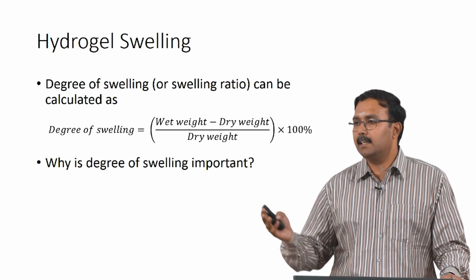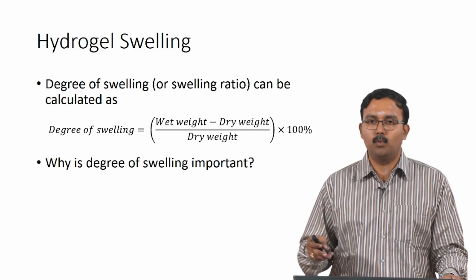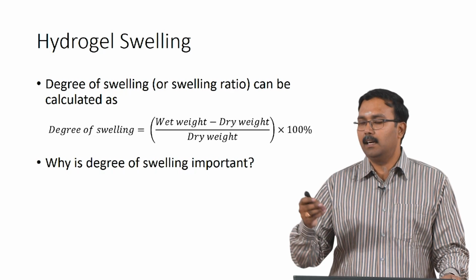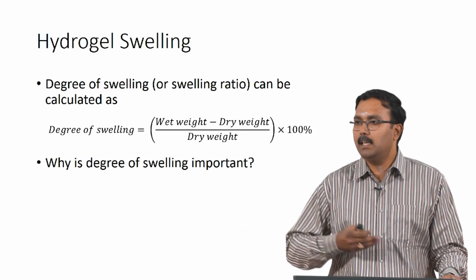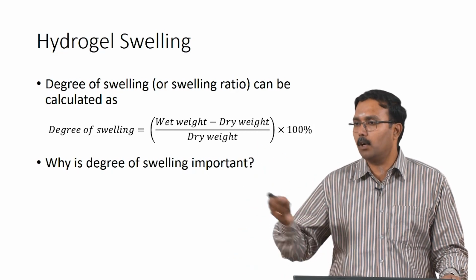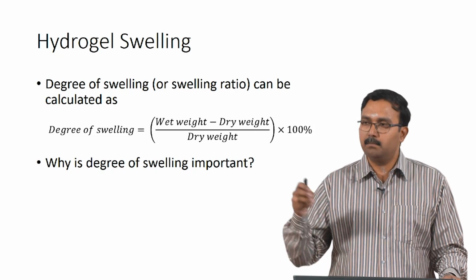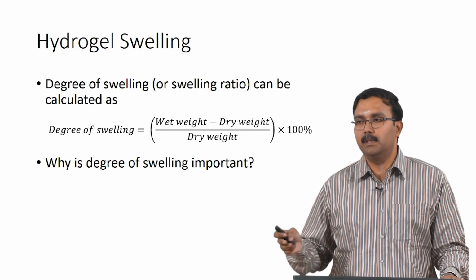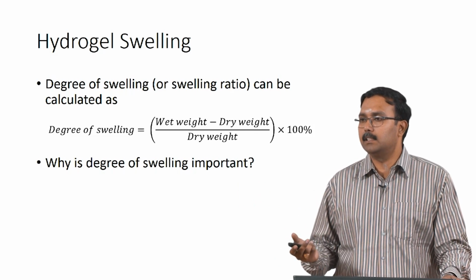You can look at swelling kinetics, which is basically taking the dry hydrogel, putting it in buffer or water and measuring its weight after certain time intervals to see how the swelling progresses, or you can look at only the equilibrium swelling. So, you take it and place it in water, leave it for like 2 hours and then take it out and see what is the final state in which it is present.